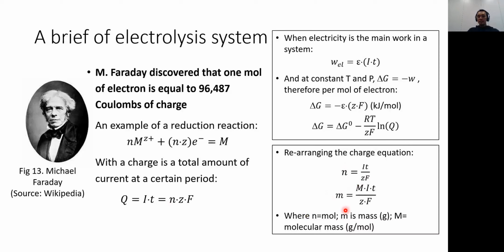So this is the very common equation that people use in electrorefining. For a process with this current that flows for 3 days, for example, if we do silver electrorefining, I have this current for 3 days. Will I have enough silver anodes to be put there? What if the silver anodes are depleted, gone in just 1 day because we put too much current there? We can calculate it from this equation easily, and this is very friendly to use.